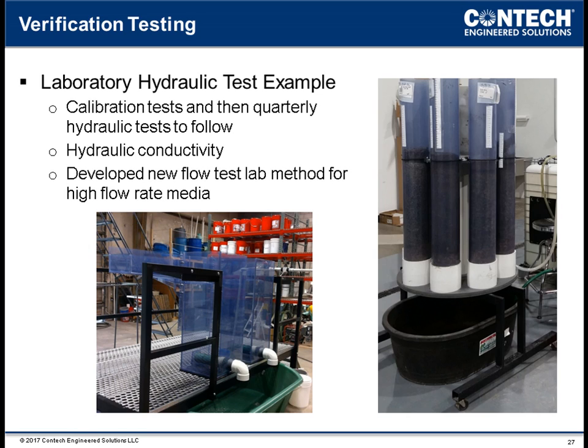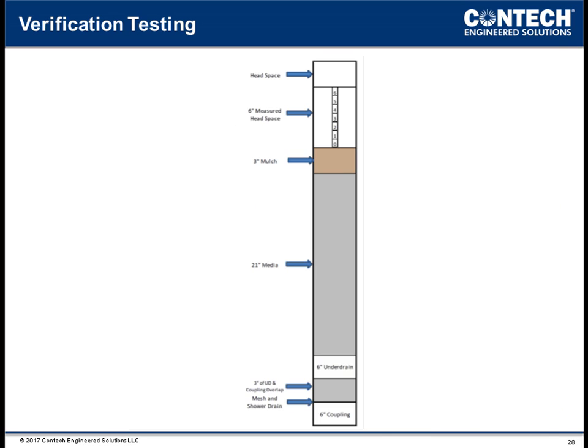Pilot scale, you can see pictured here on the left. It's the same configuration as a full-scale Filterra system. It's about 15 times the filter surface area of a column test to ensure flow rate can be duplicated in the Filterra box configuration, and there's less chance for edge effects. This is an example illustration of a hydraulic capacity SOP developed by Contech R&D. Lab-scale hydraulic testing is performed in columns just to represent the same depth of components in the system in the field.